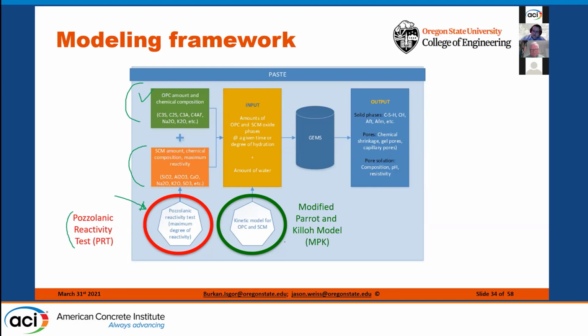The second thing we're going to do, and this was a great question from Chuck, is this is where we're going to bring in some kinetics rules. We're going to bring in kinetic models that consider OPC, and again, this is from Parrott and Killoh, and we're going to modify that to account for some of the SCMs, and there have been several papers by Deb, Glosser and Burkan that have really driven this. And we're going to now run the model, and we're going to predict the solid phases, the pores, and the pore solution chemistries that come out of this.